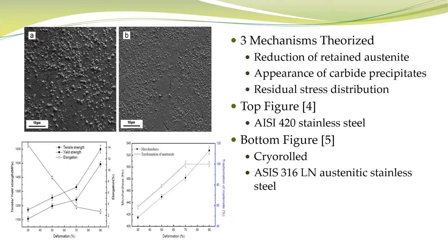As the strain energy increases, carbon atoms are swept by mobile dislocations and form clusters. These clusters are ideal heterogeneous nucleation sites, and when the material is allowed to warm back up to room temperature, this creates fine carbide precipitates that form and are uniformly distributed within the material being treated. This increases the mechanical properties of the material because it provides obstacles for mobile dislocations. The third mechanism also increases the amount of obstacles for mobile dislocations as the stress and strain state within the material increases.